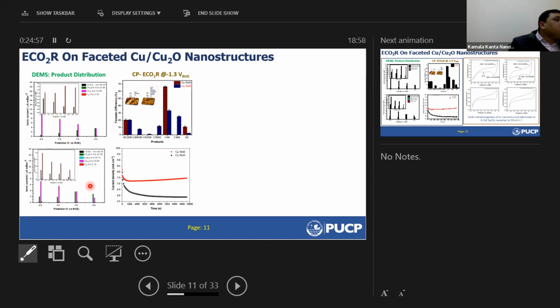Okay, but there is no particular product selectivity here, because the Faraday efficiency of the product formation is just intermediate. Although copper nanostructure A is highly selective for the production of methane, we did not want that in the beginning. We were designing the catalyst for oxygenates, alcohol production, but we ended up with methane here, and here, even though we are getting alcohols, the Faraday efficiency is very low. Okay, so therefore,